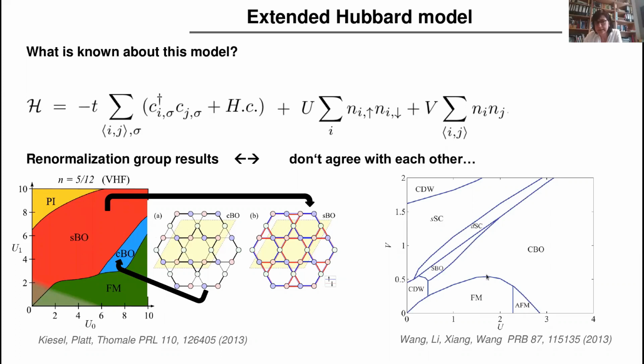So these are, in fact, two groups that investigated what kind of charge density wave phases one can expect in this material as a function of two interactions: an on-site Coulomb repulsion and a nearest-neighbor Coulomb repulsion. Here is my U as a function of V. For small values of V, these calculations find a large region of ferromagnetism, and then some different types of charge bond orders—this would be the Star of David charge bond order we're talking about, and this is the spin bond order, where we also give a spin sign to the bonds.